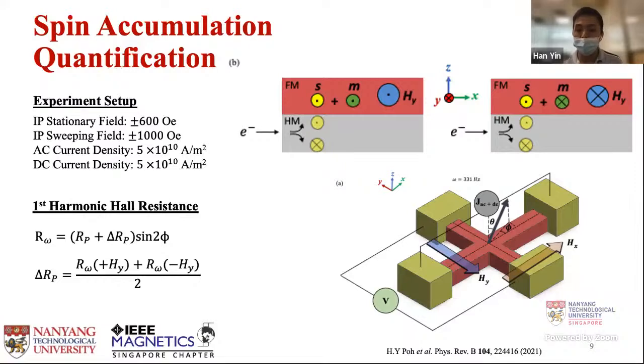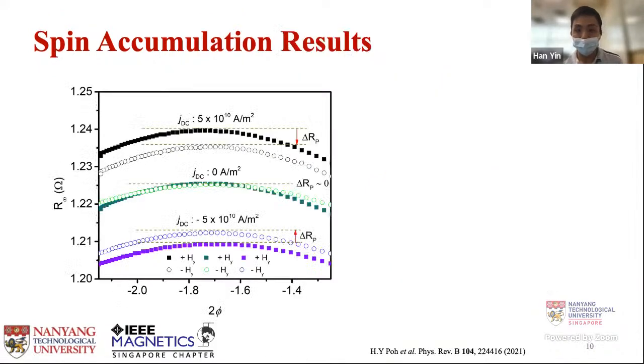This PHE includes the ferromagnetic magnetization contribution RP and the spin accumulation contribution delta RP. Like I discussed earlier, we can isolate this spin accumulation by applying an opposite direction stationary field. By summing these two, the positive field and negative field, we can isolate the delta RP, which is contributed by the spin accumulation. Over here, the results show the amplitude of our first harmonic Hall resistance. The solid symbol represents the stationary positive field plus HY, whereas the hollow symbol represents the negative stationary field minus HY.